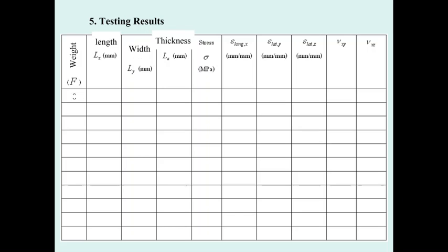The testing result will look like this. At the start, with weight equal to zero, you measure the length on the left and right of the reference mark, then measure the width at the top, middle, and bottom, and also measure the thickness at the top, middle, and bottom, and take the averages. For each subsequent loading step, you measure the width three times and take the average. You may not need to re-measure the thickness at each step — that is acceptable.